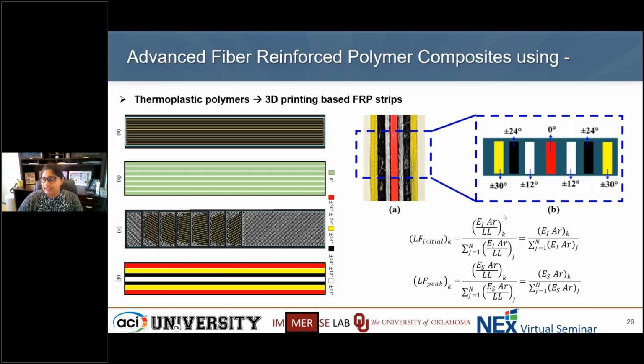So you have this mechanics related formula for axial stiffness and achieving that kind of a load fraction, where we are saying that if one lamina fails, the other should be taking the residual load. So to achieve that smooth transition, we use 3D printing and different multiple orientations to get low load fractions, because that would mean the transfer of load is happening in a smoother or non-abrupt way.